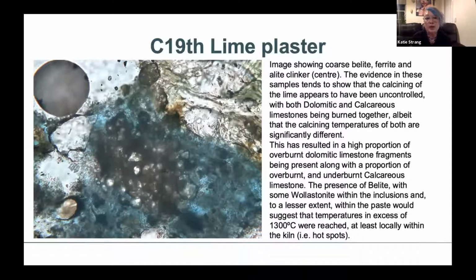Now, when you burn your limestone, if you burn dolomitic limestone, it actually reaches a clinker point at a lower temperature than a calcareous lime. So if you're putting both of those in a kiln at the same time, it's going to cause problems because your dolomitic particles will become overburnt, whereas your calcareous ones are likely to be underburnt. So essentially, in this one, we know that because of the presence of belite and wollastonite, there were in some parts of the kiln temperatures of up to 1300 degrees C, and that's the temperature you need to actually form those clinker. So we know that parts of the kiln would have been burning to exceptionally hot temperatures, way hotter than you would normally. You'd normally do about 1100 for a calcareous lime.